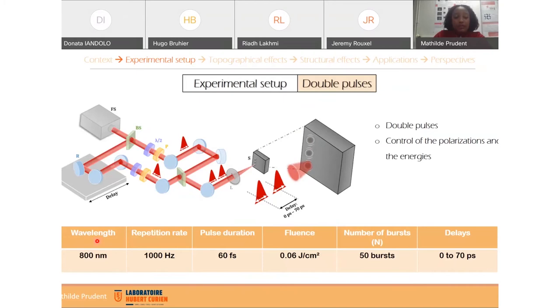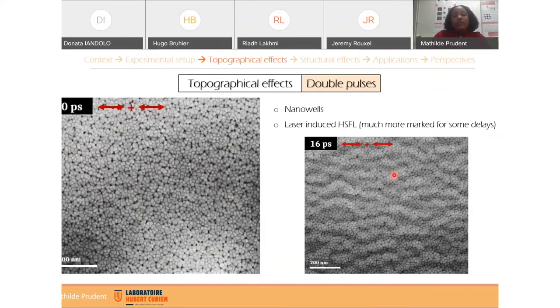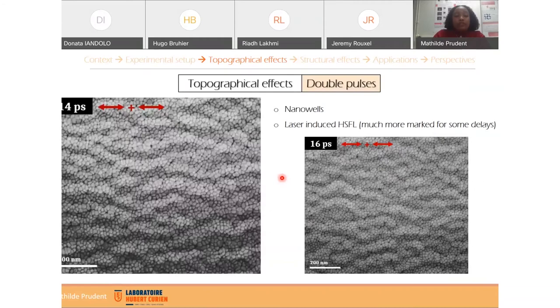So a wavelength for the laser of 800 nanometers, a repetition rate of 1 kilohertz, and a pulse duration of 60 femtoseconds. We fixed here the fluence at 0.06 joule per centimeter square, and the number of bursts was also fixed to 50 bursts. And we varied the delays between 0 and 70 picoseconds. So here you can see the results for the irradiation for the different time delays between 0 and 70 picoseconds.